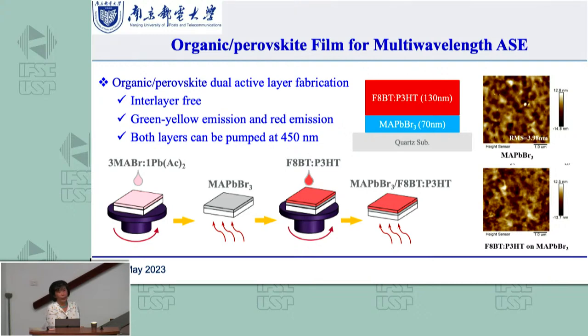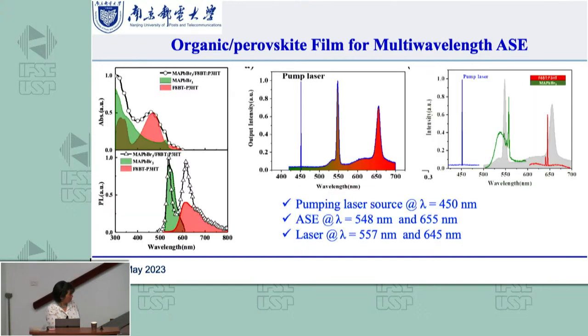we know we can do multi-layer, so we tried the perovskite with the organic layer. For the same idea, we use a two-layer material like this. But this time, we did something different. The pumping laser we chose is 450, a blue laser pumping. Then we can see the ASE from green and red. With the grating put on, we can see lasing from green and red. So together with the blue pumping laser, we can actually achieve RGB, three-color laser, with this structure.